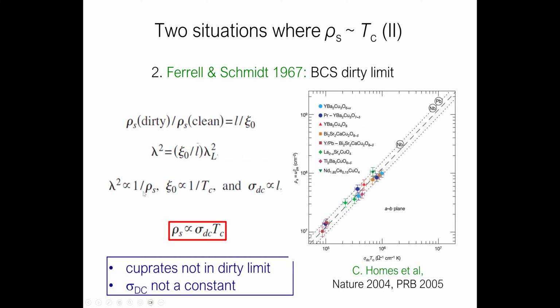Rho s goes like 1 over lambda squared, xi naught goes like 1 over Tc, and sigma in the DC limit goes like the mean free path. So put those together and you get a proportionality between rho s and sigma DC Tc. And that's a well-known result, goes back, as far as I know, to Farrell and Schmidt back in the 60s. And it's been rediscovered a few times,